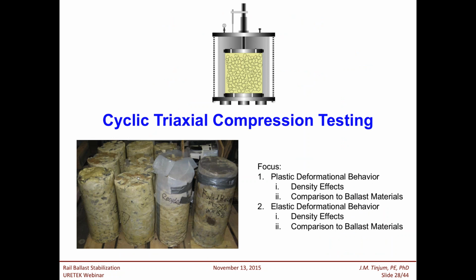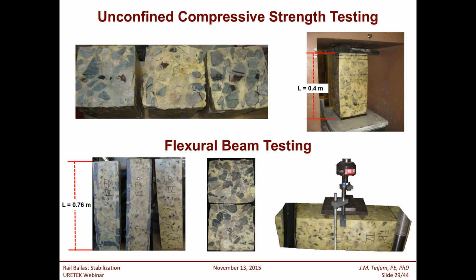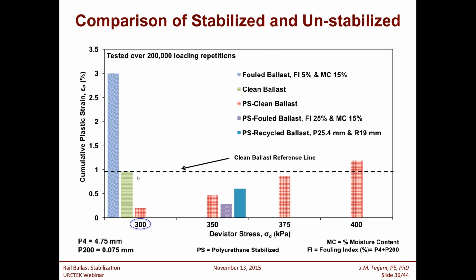And then cyclic triaxial compression testing so that we can get that accumulative plastic deformation behavior, while also measuring the elastic deformation. Just some images of the unconfined compressive strength testing and flexural beam test specimens that we have tested here in our laboratory. And I'm going to spend a few minutes on this graph right here because this is roughly the